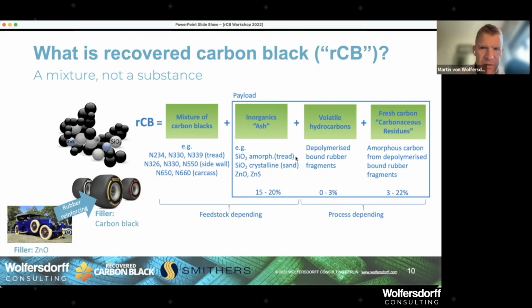Volatile hydrocarbons. The volatile hydrocarbons on raw recovered carbon black, if you don't optimize the process and you run, say, at 350 degrees Celsius only, and the residence time is not long enough, could be 10, 20%. And you can really smell the volatile hydrocarbons. But this will then not be a commercial recovered carbon black. For the commercial recovered carbon black, we need to finish the pyrolysis, and we don't expect a high volatile content on the recovered carbon black.